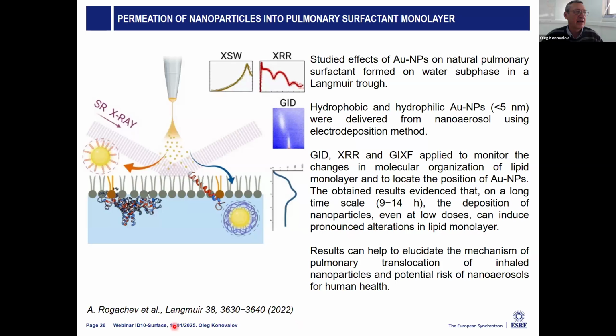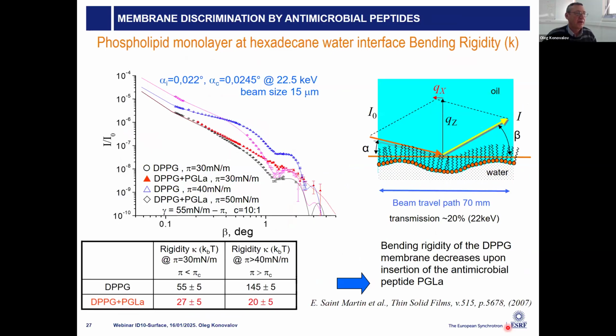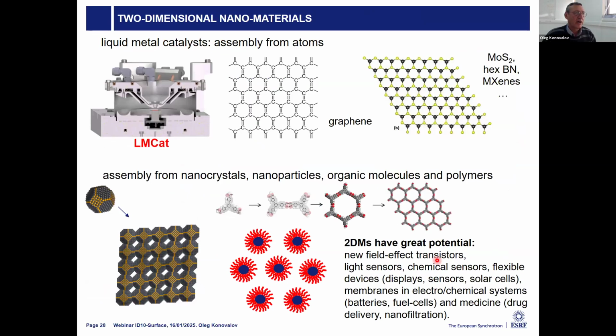This is another, more complex case where we study with all 3 techniques, fluorescence, GID, and reflectivity. We see how, with electrodeposition spray, nanoparticles, hydrophobic or hydrophilic, can penetrate through the pulmonary surfactant. So this is a mimicked layer. Then there are measurements of diffuse scattering on liquid-liquid interfaces. In this case we can also study the elastic properties of the monolayers. A lot of what we are doing, in-house and also with external users, is 2-dimensional nanomaterials, which is very important for many applications.